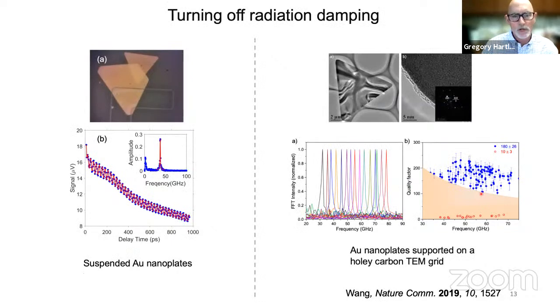And again, to do a trick of either supporting the nanoplates over a trench so that they are not in contact with anything, or it turns out you can also put the nanoplates on a very light substrate like a carbon TEM grid, and then you also don't get any effect from radiation damping. You get very long lifetimes. So this is how we do it in our laboratory, and these are some experiments done by my collaborator Kuai Yu in China, where they use TEM grids to look at the structures. And I'll show some nice data from Kuai's lab in a little bit.